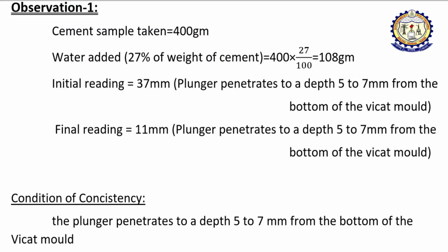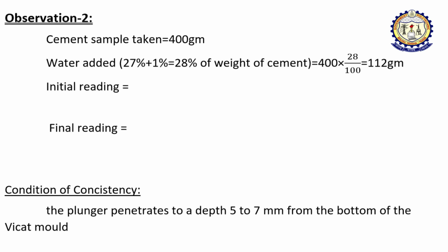In our first observation, we find the final reading is 11 mm. But as per the condition of consistency, the value should be in between 5 to 7 mm, so an extra quantity of water is required for the cement paste. Again, we start a new observation, and in this observation, we add an extra 1% of water. That is equal to 28% of weight of cement, and it is equal to 112 grams of water taken.